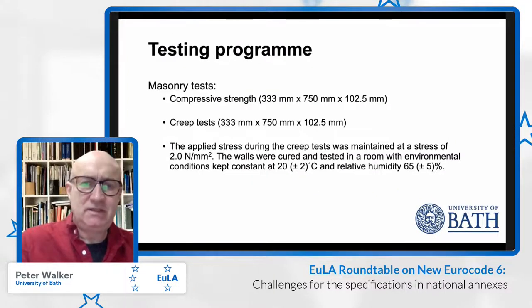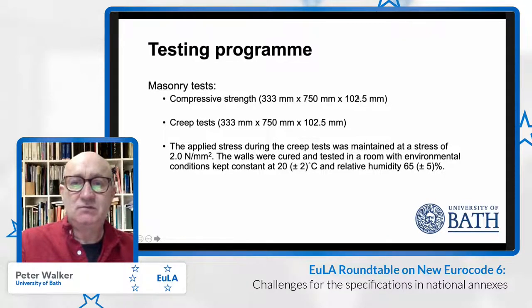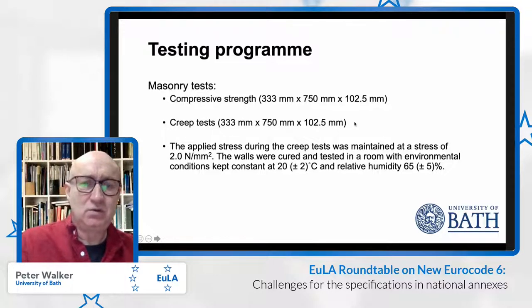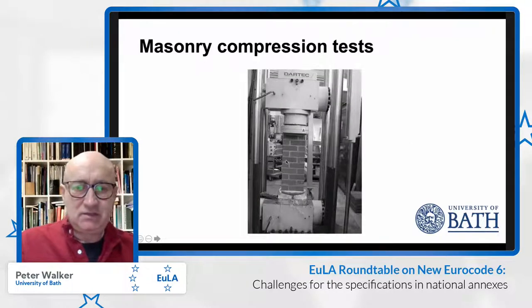And then for the masonry tests, we did compression strength tests, and we'll see some photographs in a moment. So these are the dimensions of the walls, creep tests on the walls as well. And the creep tests were undertaken primarily at a constant stress of 2 newton per square millimeter, to represent a normal service load stress within the masonry. And once cured, they were tested in a room with steady state environmental conditions again. So here is just a photograph of the compression strength test.